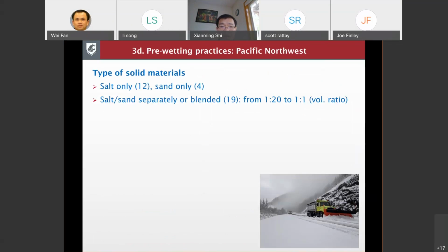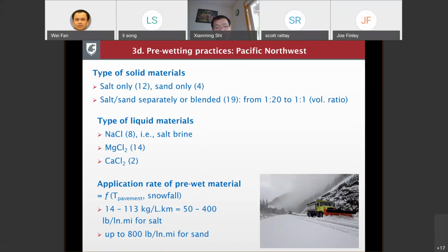Now, we're also seeing that most people actually use salt, sand, as well as salt-sand blends, depending on the situation, and the blending ratio also differs greatly. And again, we're seeing the same kind of liquids being used. The application rate of the pre-wet salt is truly a function of pavement temperature and snowfall intensity. So typically, according to the survey responses, we're looking at 50 to 400 pounds per lane mile for salt. And for sand, it's up to 800 pounds per lane mile.